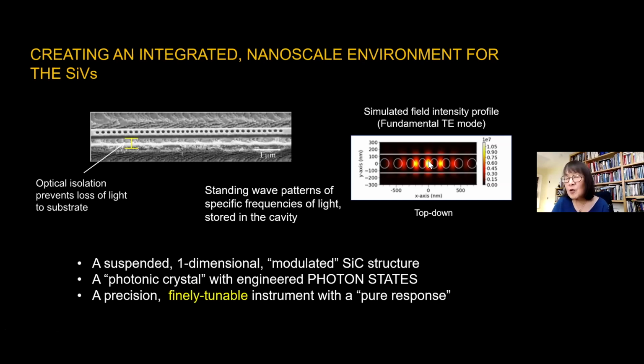That is, the standing wave patterns show you concentrations of very high electromagnetic field that are in these regions about 100 nanometers apart from each other. And what you see basically are very high regions of electromagnetic field that are localized in volumes of about 100 nanometers cube. So very high field in a very small volume.